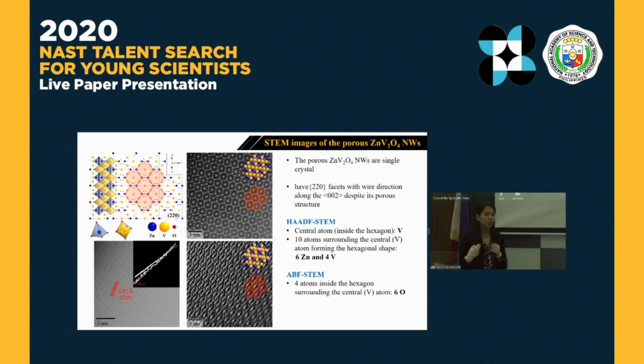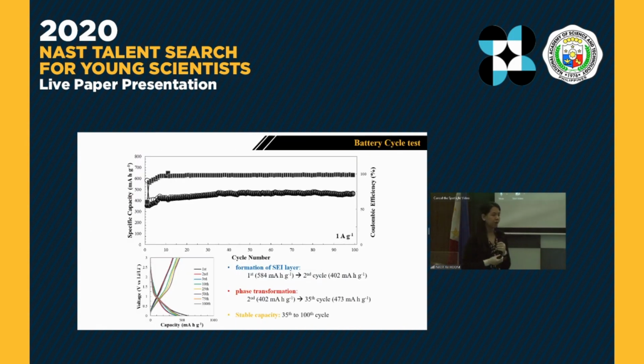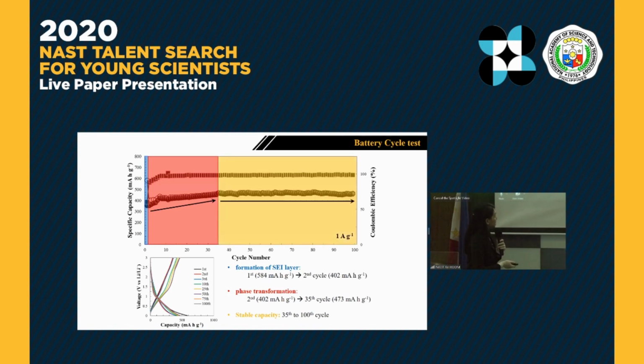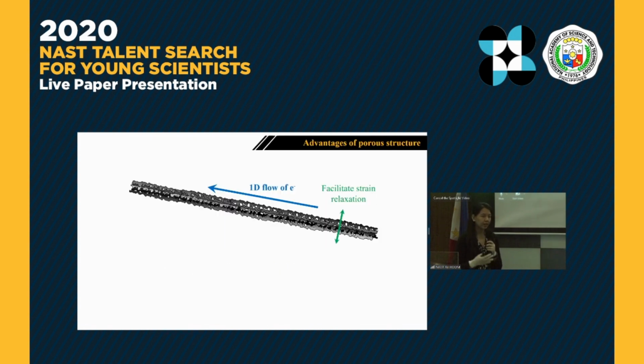These porous ZnV2O4 were utilized as anode material for lithium-ion battery. Based on our result, there is a sudden decrease in the capacity from the first to the second cycle. This can be attributed to the formation of the SEI layer. On the other hand, from the second to the 35th cycle, there is a gradual increase in the capacity, which can be attributed to the phase transformation. And lastly, above the 35th cycle, we have a very stable cycle until the 100th cycle, which makes it an efficient anode material for lithium-ion battery.